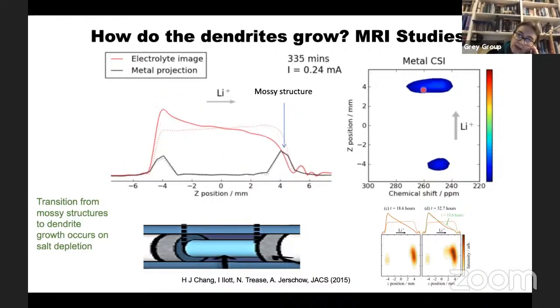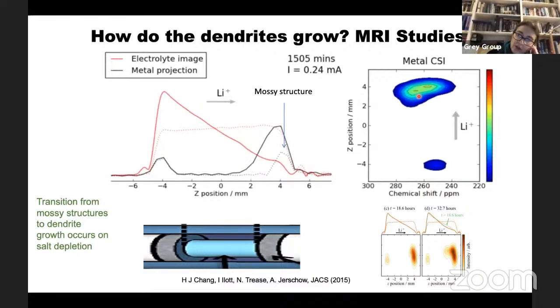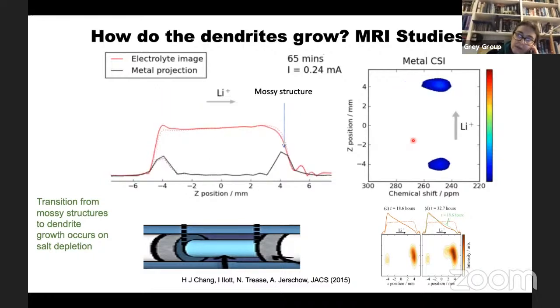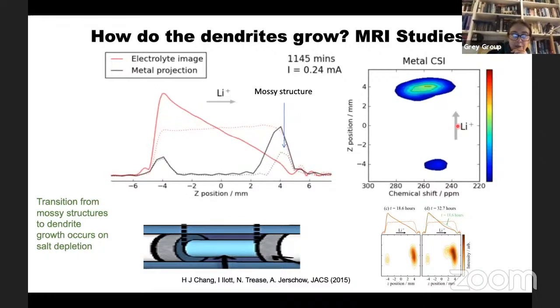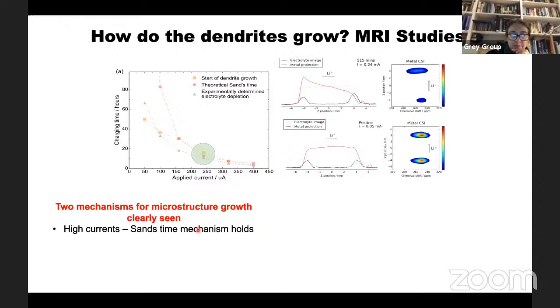And you can see that more clearly in the CSI. Here's the mossy structure, and there's the dendritic structure. Now, why does this happen? It happens due to a phenomenon quantified by the so-called Sand's time. The Sand's time is when the concentration of the electrolyte near the electrode is depleted. At that point, you get an electric field or a space charge that pulls your dendrite away from the current. And we can predict that based on knowing the diffusion coefficients for lithium and PF6 in our solution.